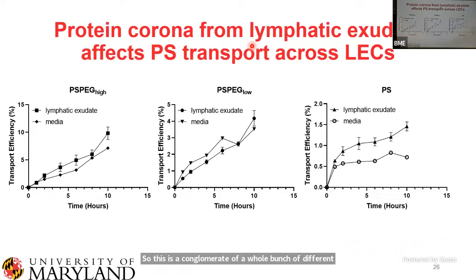And in a nutshell, when you have PEG particles pre-incubated in exudate, it didn't seem to make a whole lot of difference, at least not initially. You still see the same trends. You can appreciate here that the axis on the Y is a little bit of a different scale depending on which particle system you're looking at. So you've got your high density pegylated particles with the most transport compared to low density pegylated particles. But kind of interestingly, for the polystyrene particles, so these are really hydrophobic, highly negatively charged particles,